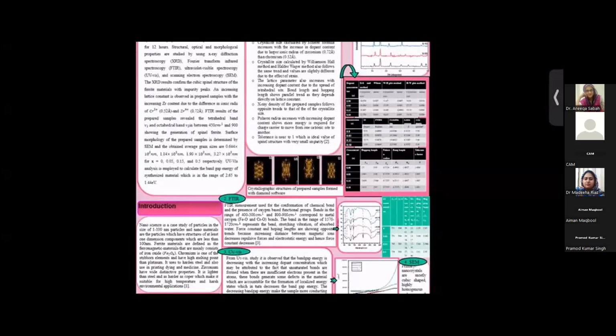increases, which shows more energy is required for the charge carrier to move from one cationic site to another, and the tolerance factor is near 1, which is the ideal value for the spinel structure with very small or no impurity. Here are the crystallographic structures obtained with the Diamond software.